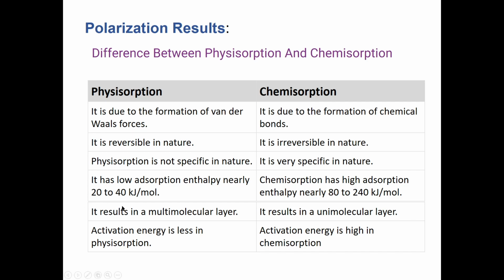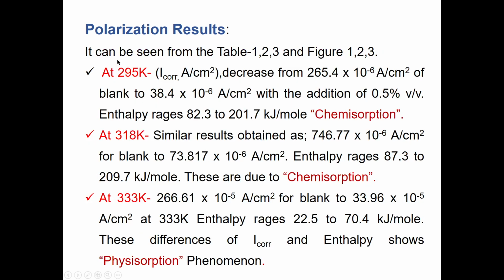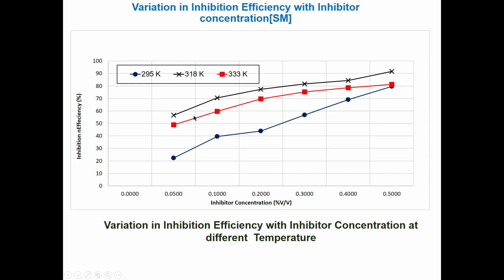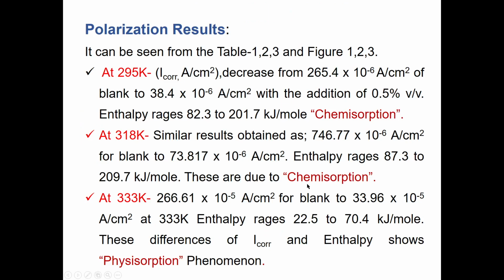So that's why the inhibition efficiency was reducing at a higher temperature. Also, you can see that the range of the enthalpy is 20 to 40 in the case of physisorption, and from 80 to 240 in the case of chemisorption. So this confirmed that at temperatures 295 and 318, the chemisorption phenomenon was occurring, and at higher temperature the physisorption phenomenon was occurring. And that's why at that temperature the inhibition efficiency reduced, because of the reversible adsorption phenomenon.